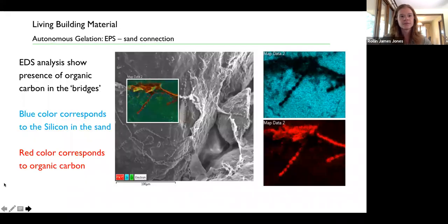Next slide. So then I used the EDS just to reinforce the idea that we were looking at EPS. On the right are EDS maps for silicon and carbon. The blue represents the silicon, and the red represents organic carbon. So we confirmed that we're looking at an organic carbon structure. Next slide.